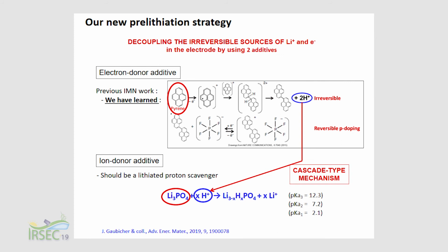So we propose to use very simply Li3PO4, which is a base with a large lithium content. And this base has an acidity constant pKa, which is very high. So it should capture efficiently the protons from these reactions and release lithium ions with this very simple acid-base reaction.